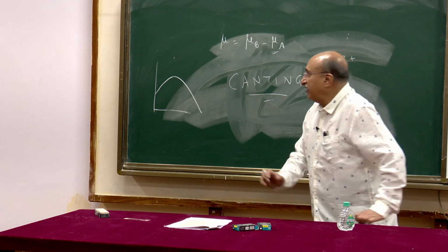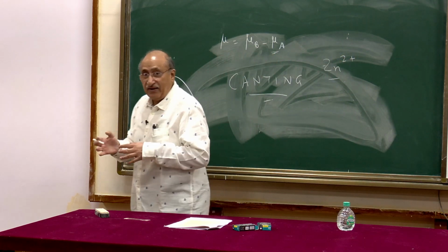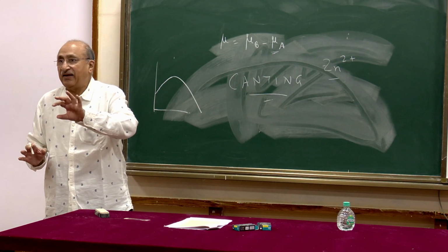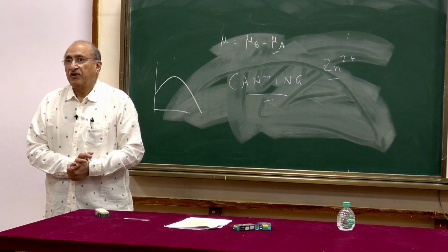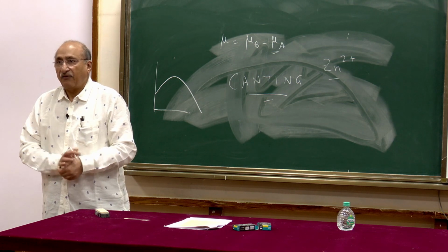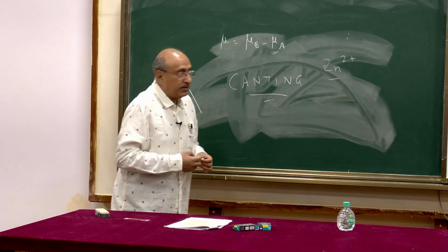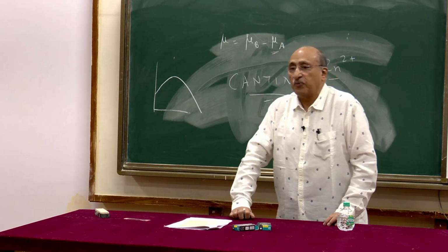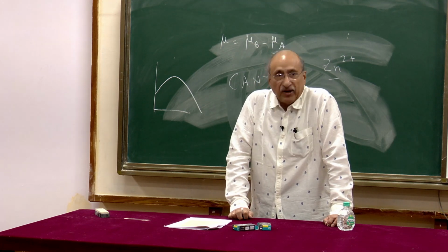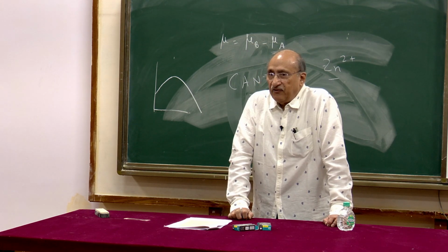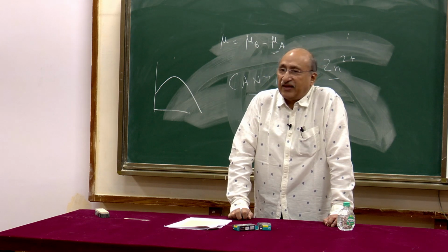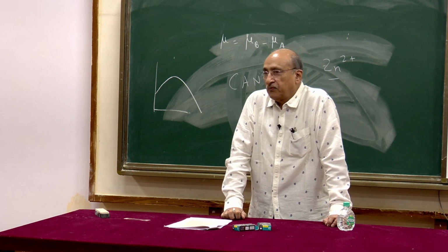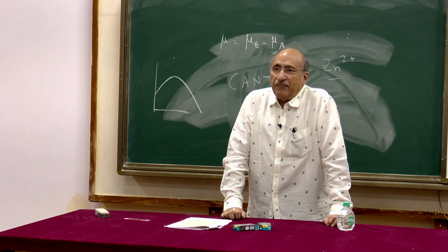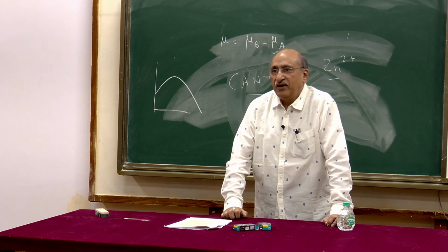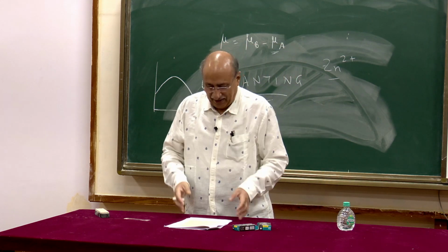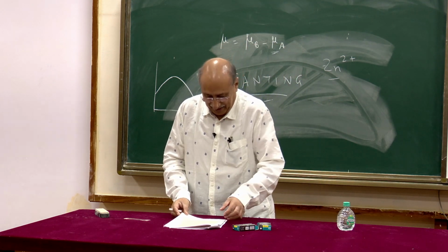Essentially, the idea is that in that case, the preference of zinc for the A side gets lost, and some of the zinc ions also go on the B side. We have seen that in our own group, and there have been reports before that, Professor Narayanaswamy's group in Chennai, on powders, a very highly quoted paper of his, where they have shown that zinc ferrite becomes magnetic when the particle size becomes very small. So these preferential sites also change when you are making the material in nanocrystalline form. That's why there is a lot of interest in thin films and nanocrystalline materials.